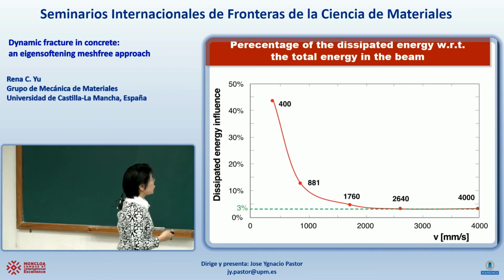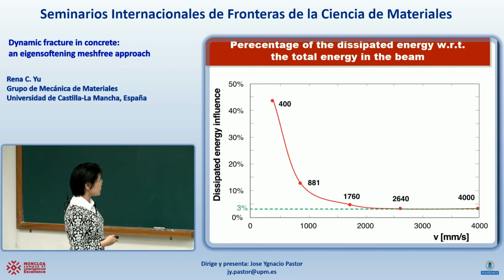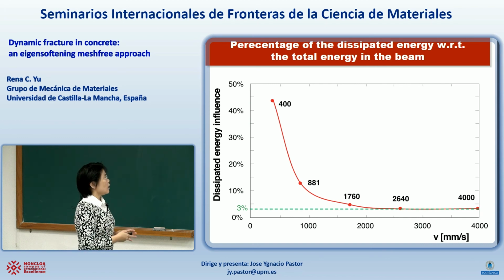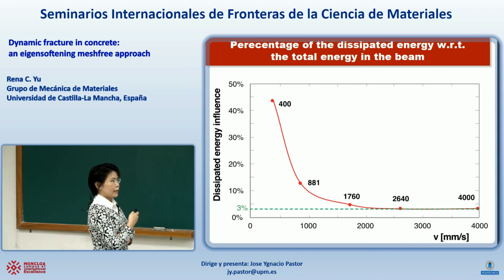And one thing I would like to emphasize is that we also do parametric studies for 400 millimeters per second velocity, and we see that the percentage of the dissipated fracture energy as part of the total energy when the velocity is great is only 3%. The significant part is the kinetic energy.